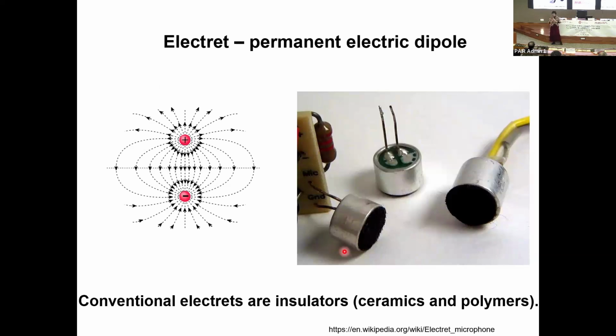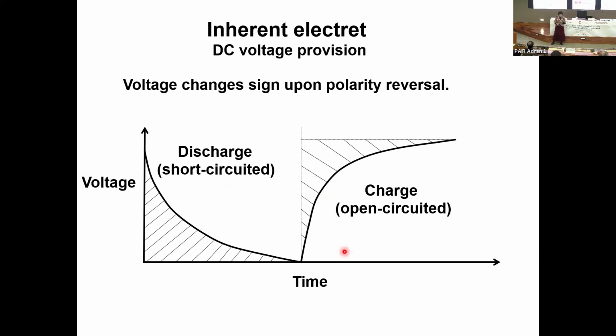Electret refers to a permanent electric dipole. Okay? And conventional electrets are all insulators. And inherent electret is what I want to talk about. That is, you don't need to pole it. And it gives a small voltage, not a big one, and the voltage changes sign upon polarity reversal, as you would expect. And so this voltage is inherent, but then you can kill it by short-circuiting it. It would discharge. And after that, if you open circuit it, it will come back. This is self-charge.